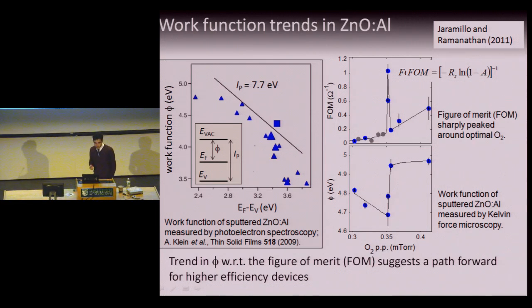I started by taking a much more narrow view of this, which is, what happens right around optimum? Because this is what we care about. When I was talking about changing the oxygen content, you go from conducting but not transparent to transparent but not conducting. Right in the middle is a sweet spot, growth conditions. This is the figure of merit as a function of oxygen content, and you see it's very sharply spiked. So if you're running an industrial process, you want to be right here. You really want to have that oxygen content tuned very precisely.